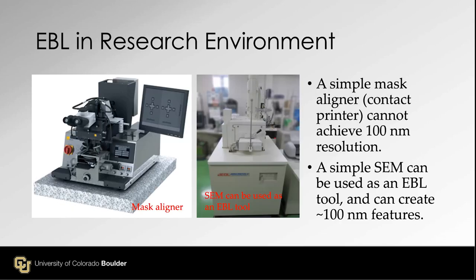Let's think about e-beam lithography in a research environment, meaning universities. Many fabrication facilities should have a mask aligner. It's a contact printer, which can be used for MEMS device fabrication. A simple mask aligner or contact printer, it has a different name, cannot achieve 100 nanometer resolution, period. Because we are using G-line or I-line mercury, about 400 nanometers, with a diffraction issue, you cannot make 100 nanometer features with a simple mask aligner.